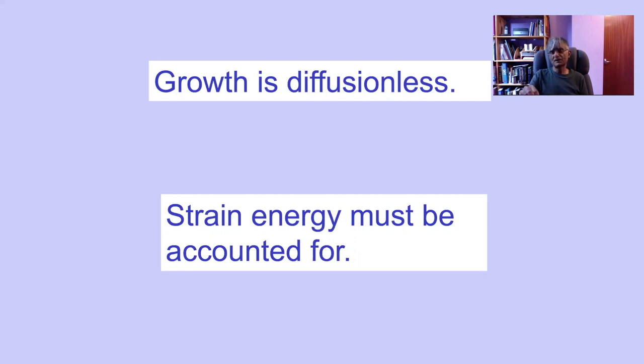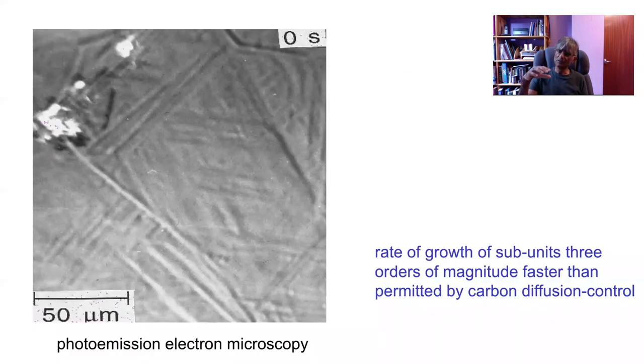There is a technique called photo emission electron microscopy, where you can put a bulk sample into a machine, an electron microscope, and you shine UV light onto it, and that causes it to emit electrons, and the sample is hot. In other words, you can make it austenitic inside the microscope. And then those electrons that are emitted, you treat with the same sort of lenses as we do in normal electron microscopy, so the resolution is much higher.